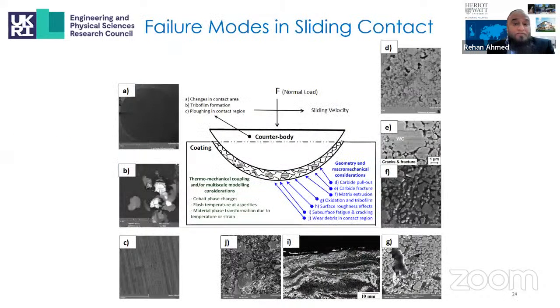So the failure modes of these coatings in sliding wear can be classified in 6 main categories. So the first one is the carbide pullout, where the carbides are just simply extracted, or they leave the matrix. Carbide fracture, which is shown as transgranular fracture in this particular case. Preferential wear of the matrix, leading to the exposure of the carbides, and the importance of the protective tribofilm, which not only depends upon the counterbody material, but also the tribological test conditions.